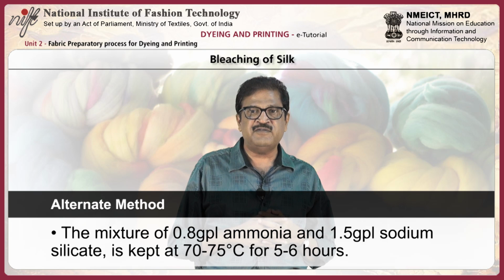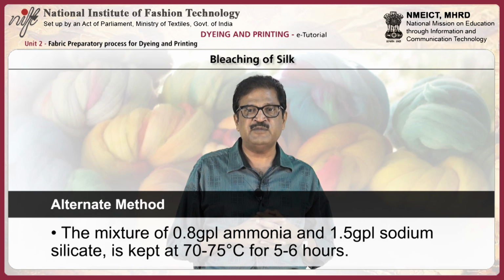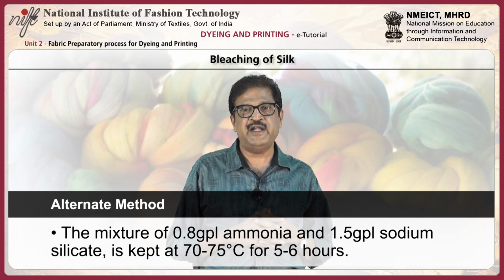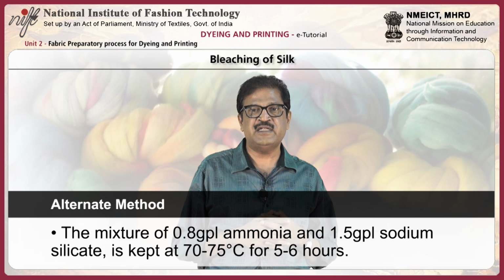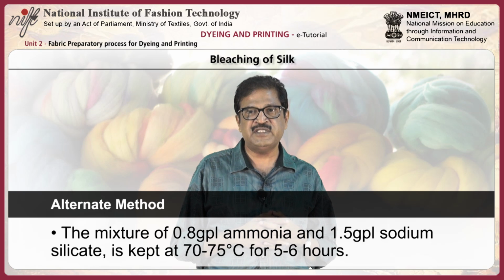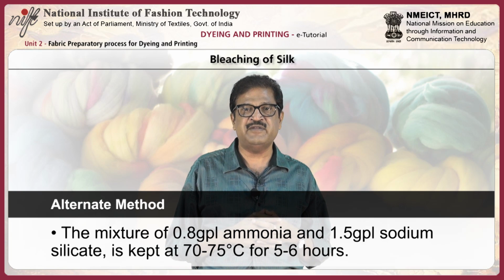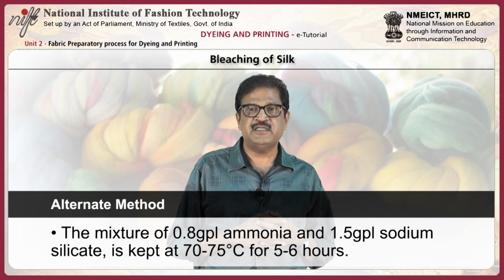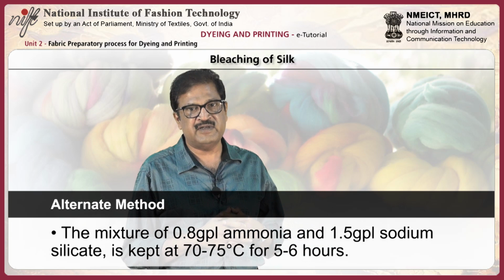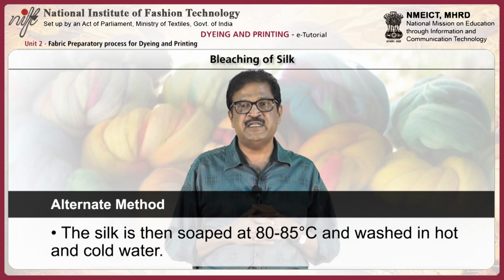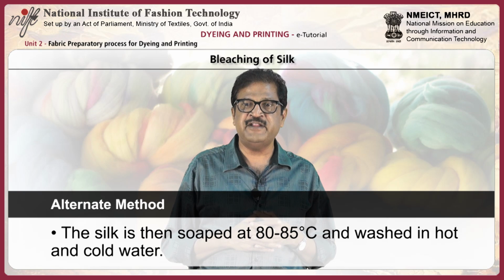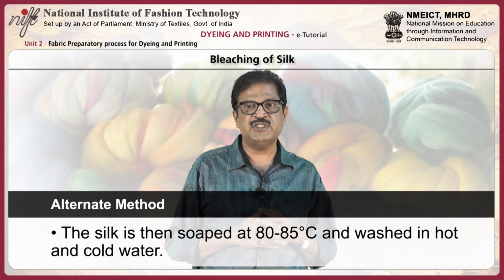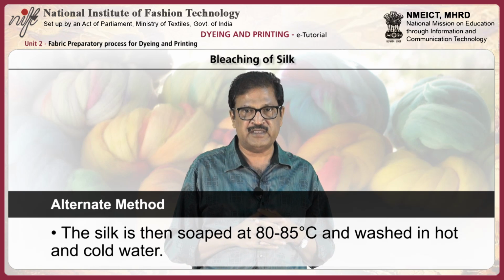Here the mixture of 0.8 grams per liter ammonia and 1.5 grams per liter sodium silicate is used, the temperature is kept at 70 to 75 degrees and time duration of 5 to 6 hours. The silk is then soaped at 80 to 85 degrees centigrade and washed in hot and cold water.